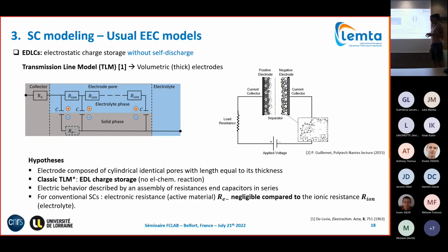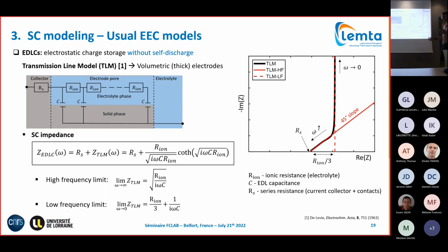electron conducting resistances. Note that in conventional supercapacitors, the electron resistance is normally negligible compared to the ion conducting resistance, and is therefore generally neglected. You complete this transmission line with a series resistance linked to the current collector and different interface resistances. That's our circuit. If you solve this circuit in the frequency domain, you end up with this expression. This impedance expression depends on different parameters shown here in the circuit, and on the frequency.